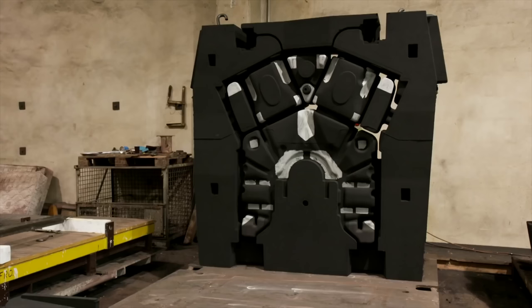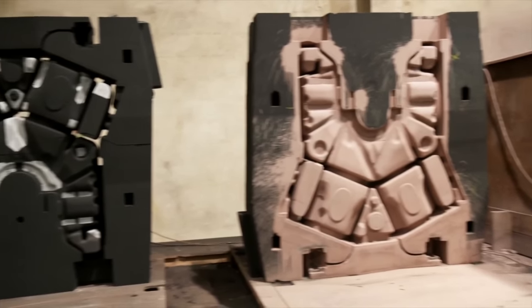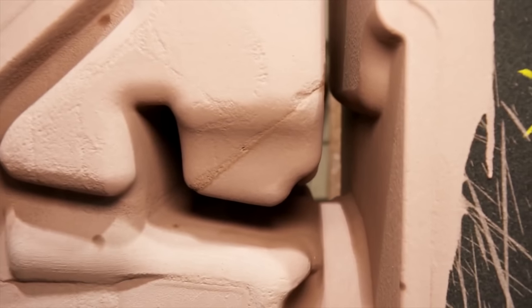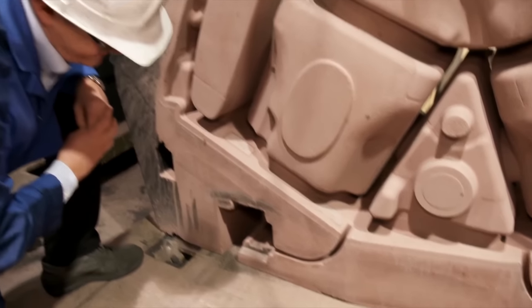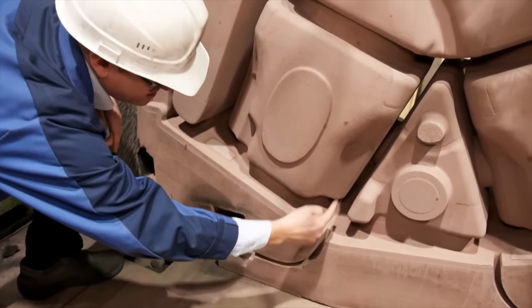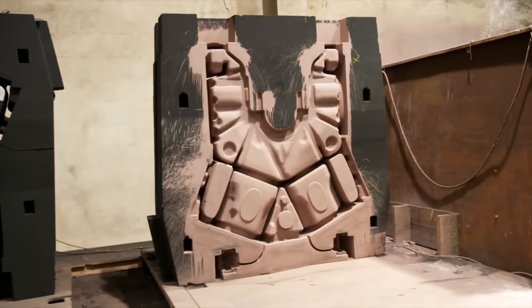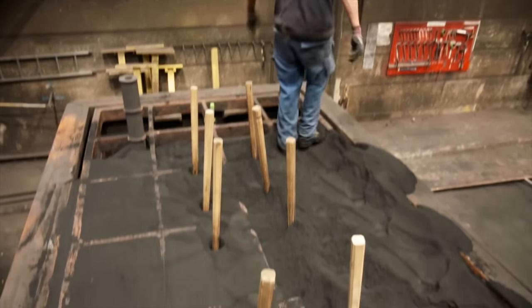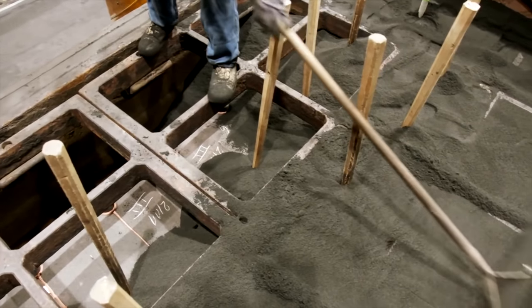The single-component casting mold is made of resin-soaked quartz sand which, after hardening, becomes even more durable than stone. Ten individual cores make up the entire casting mold for the mega engine's crankcase. Prior to casting, each mold is coated with an intermediate layer that emits a strong odor, serving to prevent sand from adhering to the steel. As molten steel flows into the mold through a channel, it passes through a ceramic filter and enters via a series of carefully placed gating systems. Once the ten individual cores are placed inside the framework, workers fill it with sand, as without it the mold's components could be violently ejected during casting. This filling procedure demands skilled workers, as any inaccuracies may render the mold unusable.